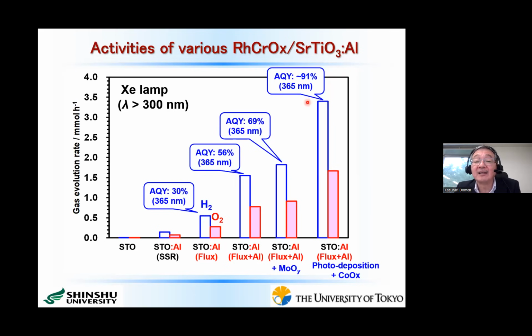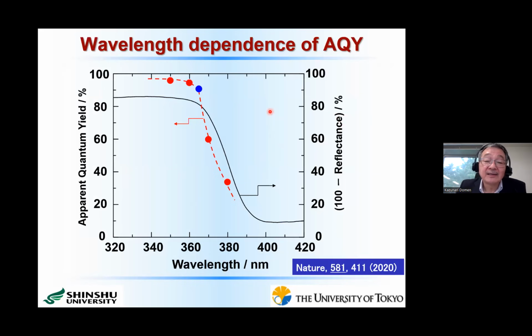So now let me discuss a little more in detail about this photocatalyst. Okay, this is the wavelength dependence of the apparent quantum yield. And this is the data that I showed in the previous slide, at 365 nanometer, 91% of AQY. We also measured at different wavelengths as shown here. Now, apparent quantum yield was evaluated based on the total photon number which was introduced into our reactor. That means that some portion of the introduced photons are scattered out without being absorbed by our photocatalyst.